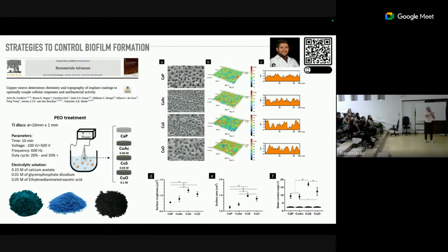We also checked some drug delivery surface, but this is not under control. We just developed a surface coating containing copper, from different sources of copper, such as copper acetate, copper sulfate, and copper oxide, using plasma electrolytic oxidation, as you can see here. And we also used a control, calcium phosphate only. In all the surfaces we observe a volcano-like surface, with pores in different sizes and numbers, depending on the electrical conductivity of the solution that we use to prepare this coating. The number and size of the pores vary quite a lot across the groups.